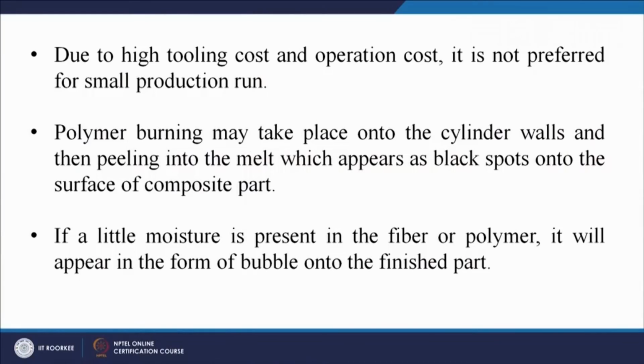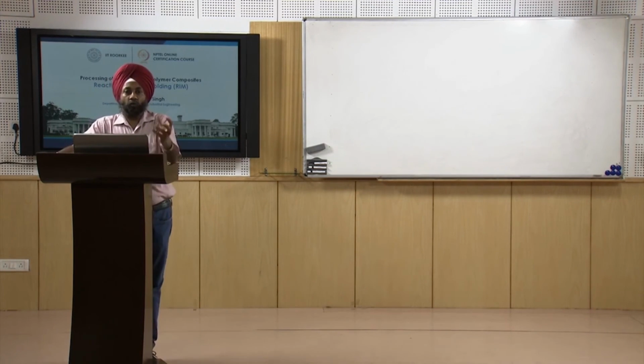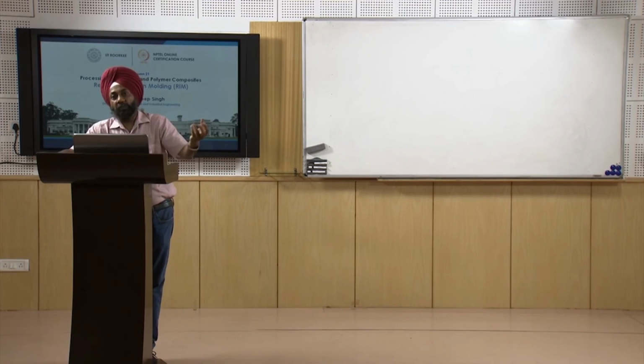And if a little moisture is present in the fiber or polymer, it will appear in the form of bubbles in the finished part. So usually it is advisable that when you are going to go for injection molding, the constituents or the raw materials must be put in an oven for a specific duration of time at an elevated temperature to remove all the moisture. Otherwise this moisture may appear in the form of bubbles on the final composite product. So that has to be avoided. There are methods to avoid these kinds of defects.